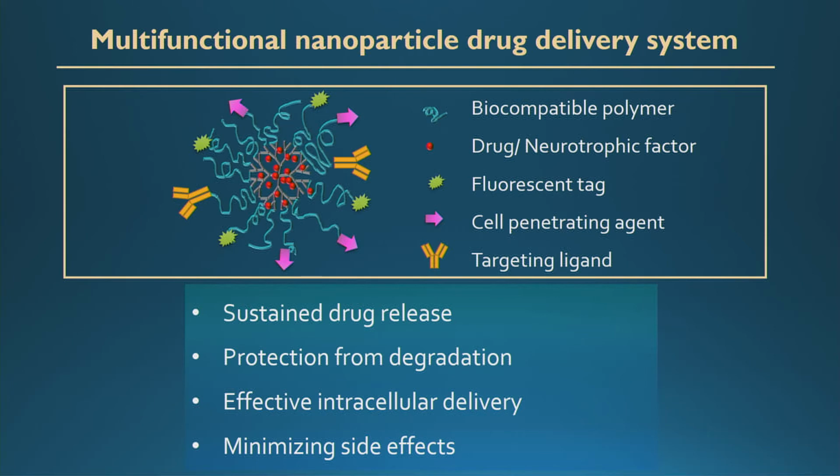The advantages of nanoparticles are, again, that they have very defined chemistries and you can do a series of modifications. I have some examples in that illustration there. But you can also add smart materials that react to differences in pH or temperature. So they're very attractive as a drug delivery system. And the main advantages are that they provide a sustained release of the drug. As the drug is encapsulated in these nanoparticles, it's actually protected from degradation. Sometimes enzymes degrade drugs, or even pH from the media. So they're more protected and can be effective for longer periods of time.